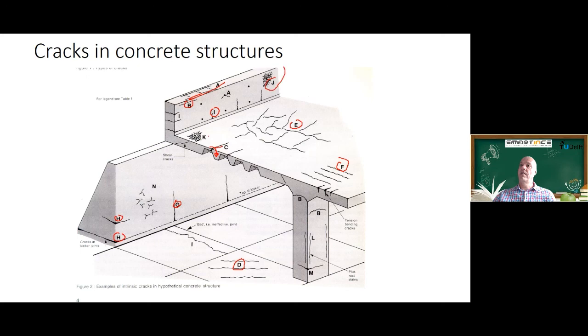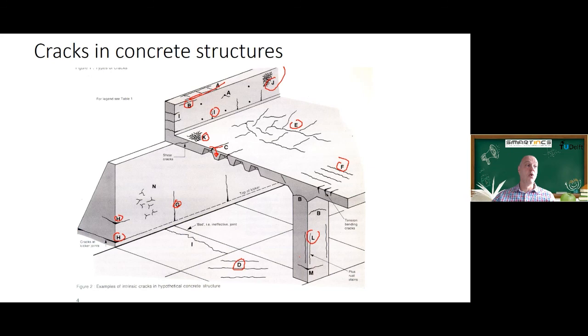Cracks J and K are also due to shrinkage and moisture loss at a later age, causing a crazing pattern at the surface. Cracks L and M are due to reinforcement corrosion, which occurs later after water ingress, carbonation, or chloride penetration causes the rebars to start corroding. They expand and cause cracking in the concrete, which can be vertical or horizontal.